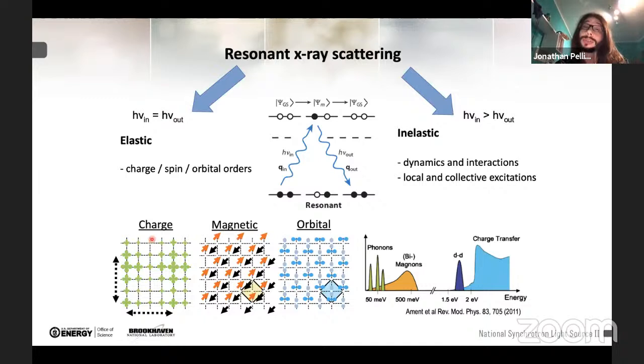In fact, when we perform what is called resonant elastic X-ray scattering, where the incident energy is the same as the outgoing energy, we can study in a similar way to diffraction, but with a sensitivity to electronic orders, all of the degrees of freedom that I mentioned before, and the wave vector of these orders, as well as their dependence on temperature and possibly also on different control parameters.